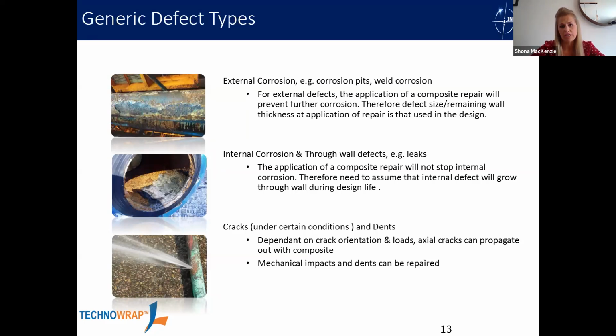The thing to consider here is that the composite repair will not stop the internal corrosion. So we would have to assume that internal defect would grow through wall during the life of that repair itself. So if we designed it for, say, 15 years, we would need to understand the rate of corrosion or make some assumptions within that design to assume that that corrosion will continue underneath the composite.